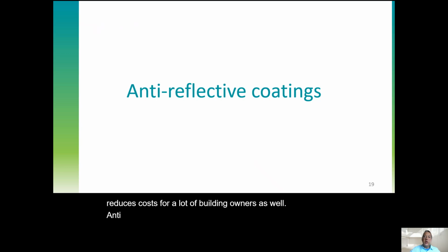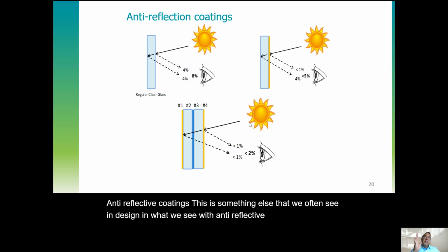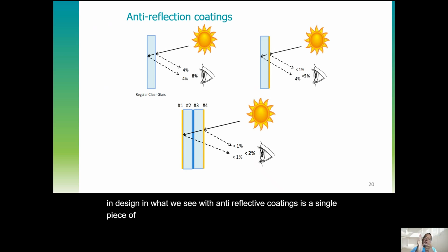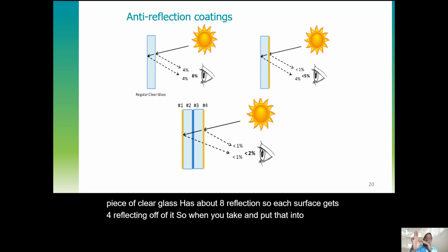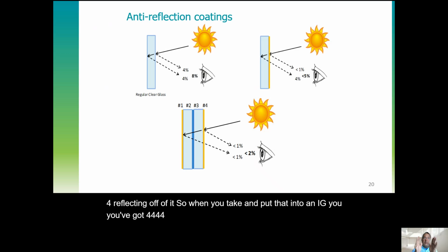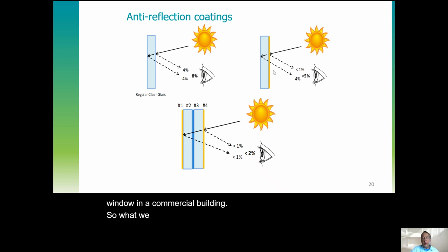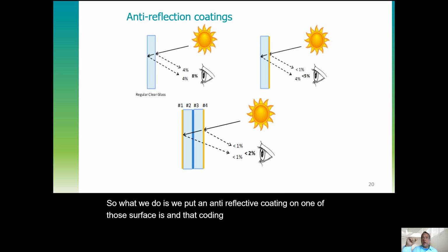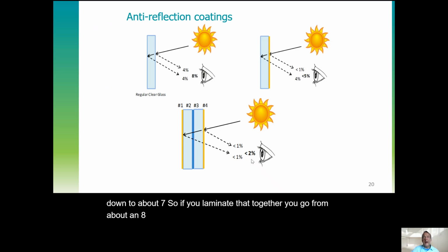Anti-reflective coatings, this is something else that we often see in design. And what we see with anti-reflective coatings is a single piece of clear glass has about 8% reflection. So each surface gets 4% reflection off of it. So when you take and put that into an IGU, you've got 4, 4, 4, 4, 16% reflectivity off of a regular window in a commercial building. So what we do is we put an anti-reflective coating on one of those surfaces, and that coating reduces your reflection from 4% down to about 0.7%. So if you laminate that together, you go from about an 8% reflection down to less than 1.5.